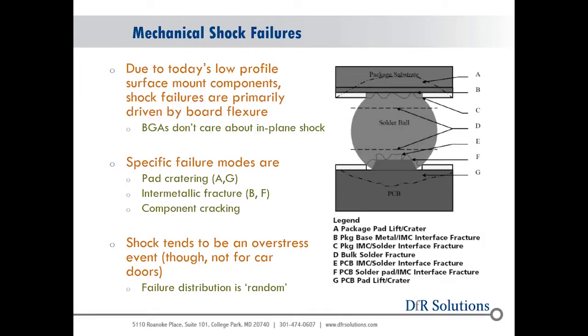A good example is BGAs, which would probably be the most common component that shows shock-related failure. For most of these parts, it really isn't the mass of the component itself. Yes, it can be if there's a big heat sink on it, but usually it's board bending. We don't really care about the mass of the part. If I shock the component in plane, the package wants to move with respect to the PCB in a shear direction, and there's a lot of solder attached. So in the shear direction, we don't really see any issues.